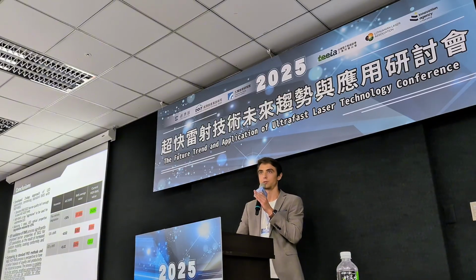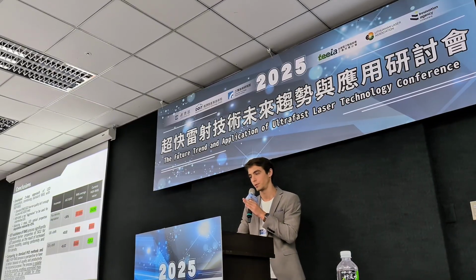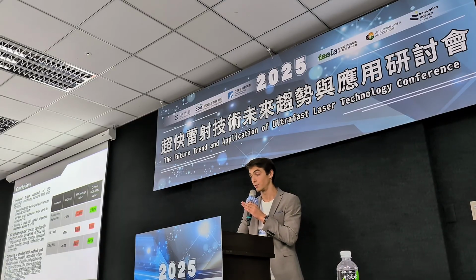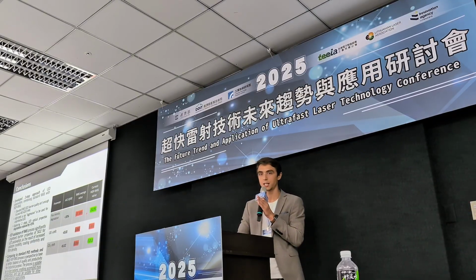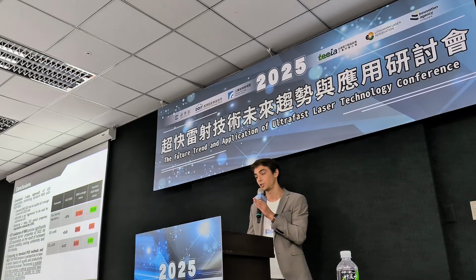The improvement in sealing properties is caused by using high-density plasma, because it makes the silicon dioxide layer more dense, and the diffusion barrier was crucial against hydrogen sulfide oxidizing the silver. Finally, high-density plasma reactive magnetron sputtering almost reached the parameters of the standard, and being very scalable, it is a good balance between standard PVD methods and the atomic layer deposition method. As you know, atomic layer deposition is a good conformal coating method, but it takes a lot of time and a lot of money.